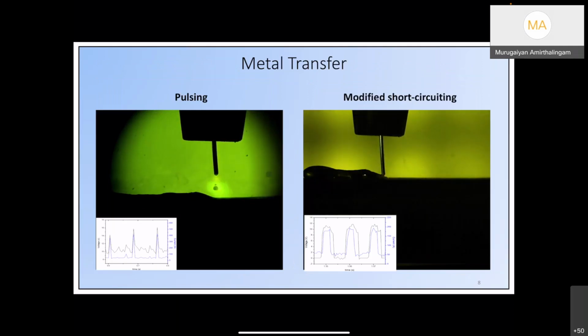And what you see over here is a high-speed video. During this process, we tend to also superheat the molten pool. So the temperature at the top of the pool and the bottom of the pool would differ significantly. That means the temperature gradient would be steeper in this case.